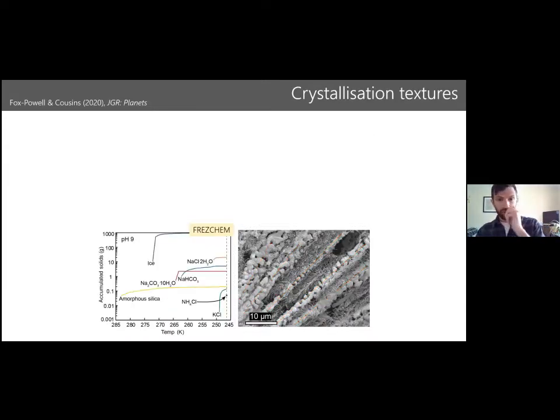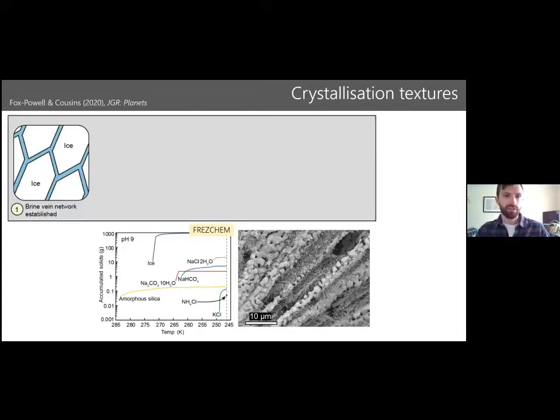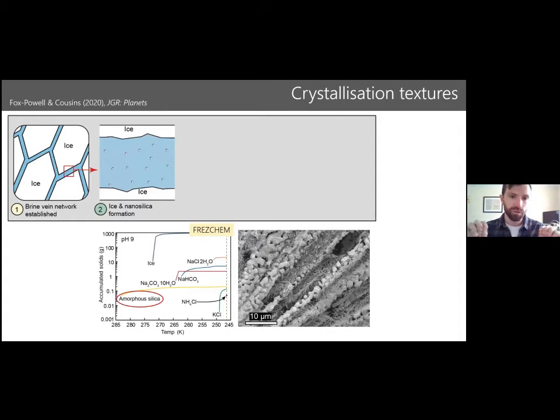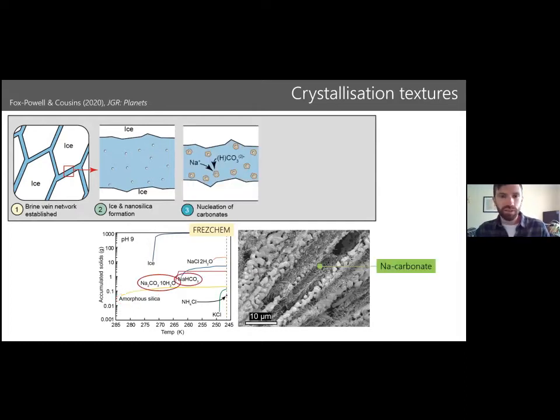We also used some thermodynamic modeling to try to tease apart and understand what's going on here. What we can infer if we compare the observations to the model is that first we get this brine vein network established, ice forms, and alongside that we precipitate amorphous silica. This forms as colloids, which are likely just a suspension within the brine veins at this point. As cooling progresses, the next phase to form are these sodium carbonates.